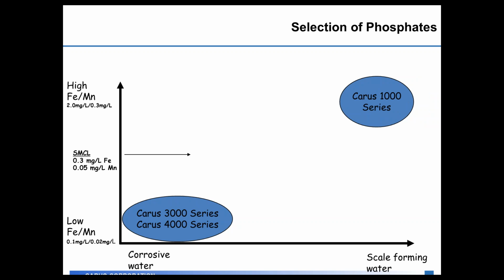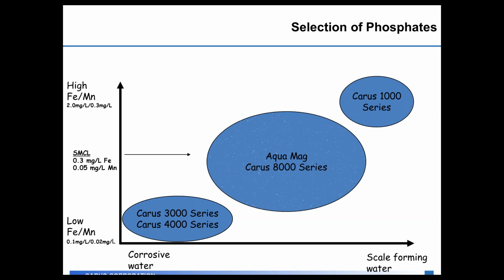If you have a very high hardness, a high alkalinity, and a high iron and manganese content, then we would be looking at a straight polyphosphate product in the Carus 1000 series. For most water qualities, we would be looking at some type of blended phosphate with both corrosion control and sequestration abilities, and this would fall into our Aqua Mag series or our Carus 8000 series of products. As you can see, there's some overlap, so there's places where you could choose different types of products and different dosages and still achieve your treatment goals. So you can choose different products depending on what you're really focused on.